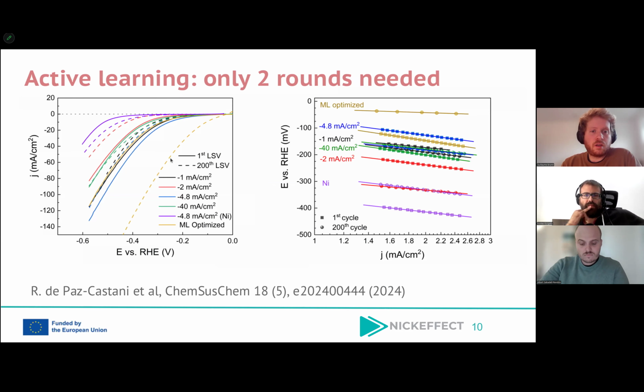So you can see here on the left, each color represents a film, and we want to be as much to the right as possible. And you see that the yellowish gold one here, the ML optimized one, is indeed the best one. You can see here as well on the right, it's the same but in different scale, that we want to be as high as possible in potential, and indeed the ML optimized is performing the best among the other ones. And so all this has been written and published in a paper here that you can go check out if you want all the details. We can also discuss during the question time later.